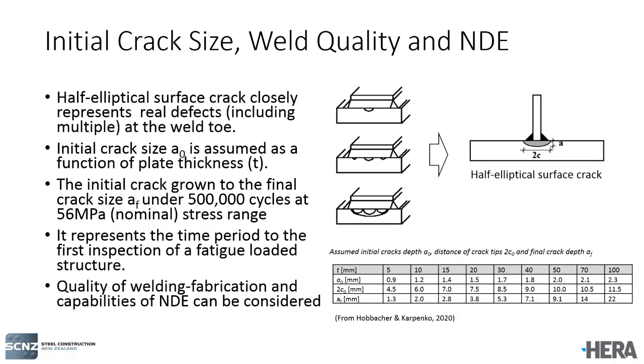Now, this crack will grow. So 500,000 fatigue cycles at 56 megapascal stress range, and this nominal stress range measured in the plate, is applied to this crack. So the crack will propagate. The reason for propagating this crack is we need to get closer to reality. We say this crack is undetectable, but the structure is loaded. It may have been loaded due to a seismic event, or due to high cycle fatigue, and we missed the crack propagation period. So crack propagation is considered by applying 500,000 cycles to this plate, and the crack will grow to the final size, identified as AF.